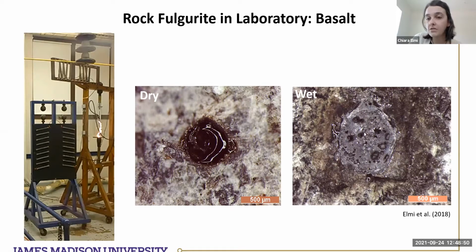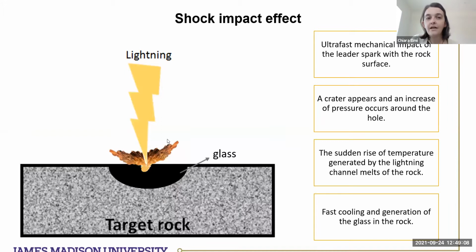So we noticed that probably the granite was wet at the moment of the lightning strike, because when the surface is wet, you see a lot of bubbles on the top of this glass, and it looks like an explosion. Most of the glass creates this rim on the surface of the rock, like in this example. So a lightning arrived at the target rock, generated this crater and vaporized a few layers of the rock, and created a shock wave that cooled down pretty fast and generated a glass on the target rock. That is mostly what happens in an explosion or a shock impact in general.